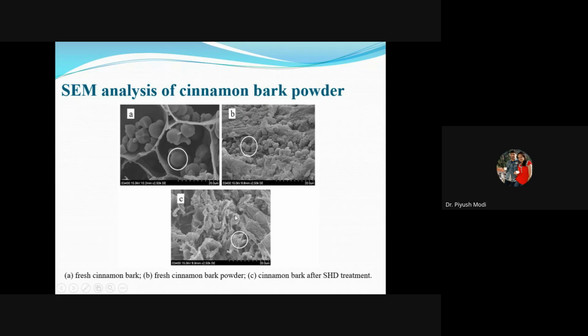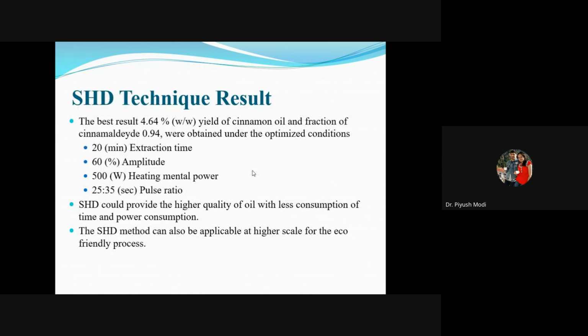The same plant material was studied afterward, so it is a microscopic study of the particular plant material. In that we get a 4.64 percent weight by weight yield of cinnamon oil, and the cinnamaldehyde fraction is 0.94.